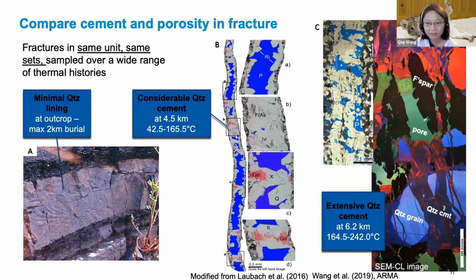Now, let's compare how the cement looks within those fractures over a wide range of thermal histories. Let's go through the 3 scenarios one by one from left to right. The left is the outcrop scenario. The rocks in the outcrop are buried to a maximum of 2 kilometers depth. And here we're looking at an open fracture surface. We see a negligible amount of quartz cement lining the fracture surface, which indicates that the fractures were generated in the subsurface, then brought up to the surface and split open in the outcrop. Figures B and C are core observations. They further show that the amount of quartz accumulation depends broadly on thermal exposure. If we compare the intermediate burial and the deep burial case, we see more extensive quartz deposits in the hottest, most deeply buried fractures.